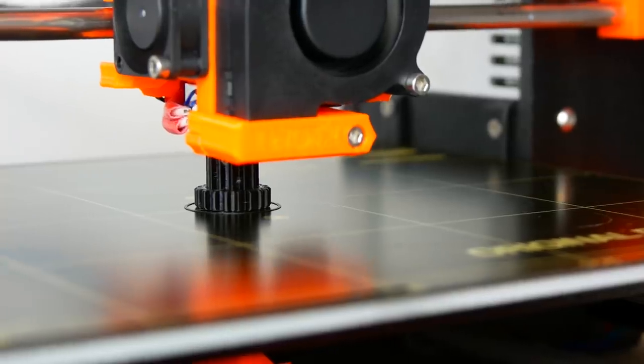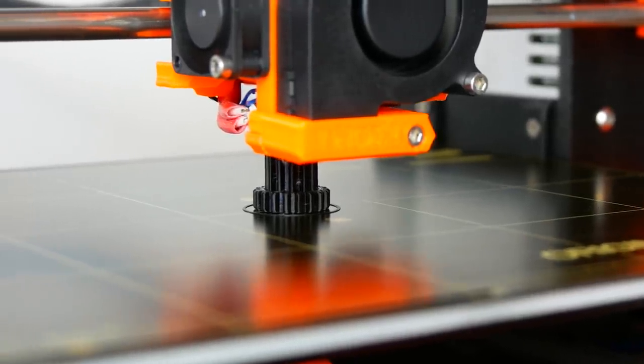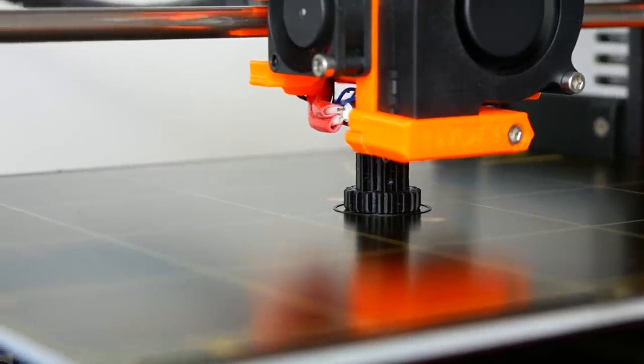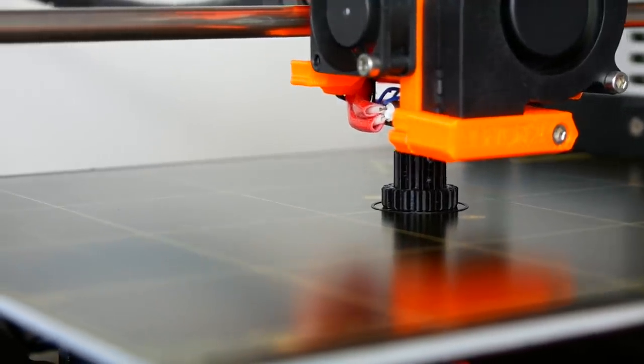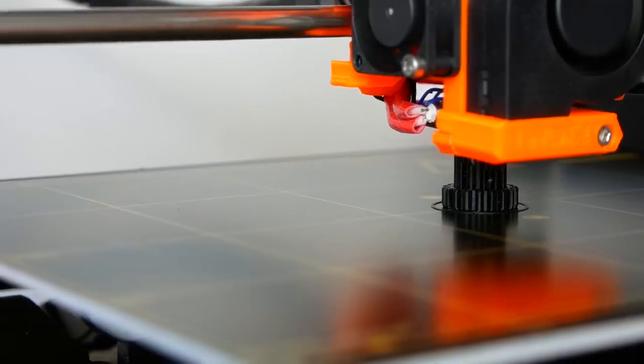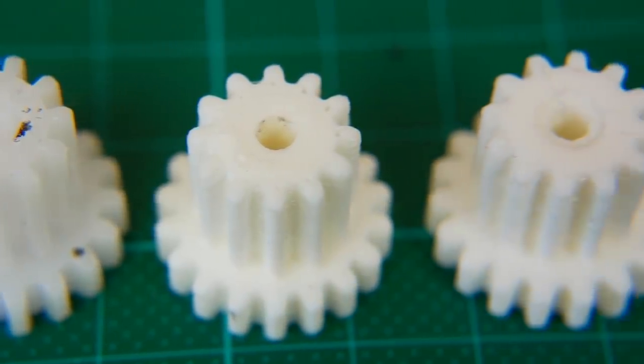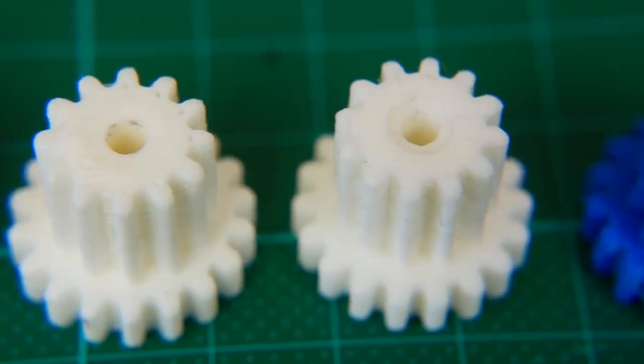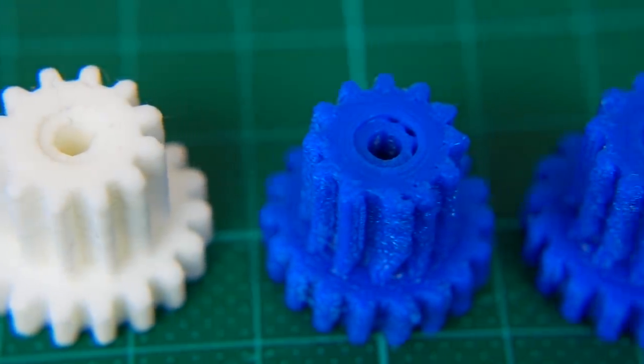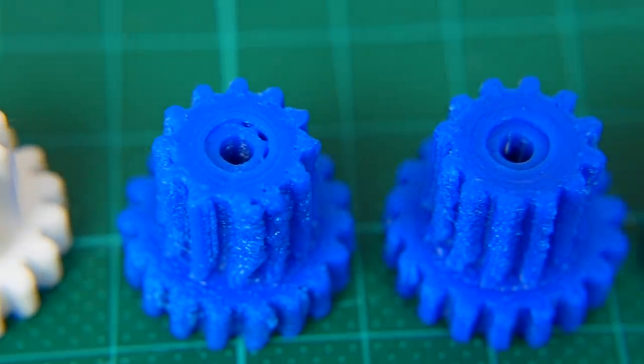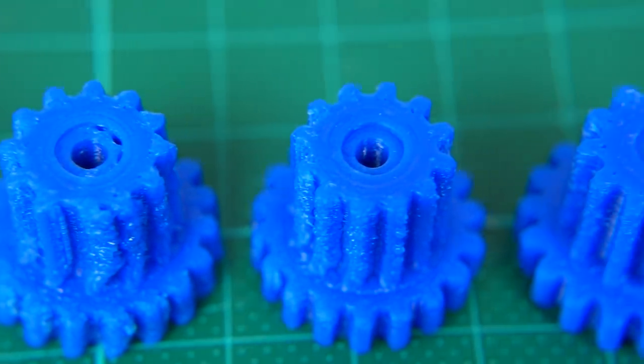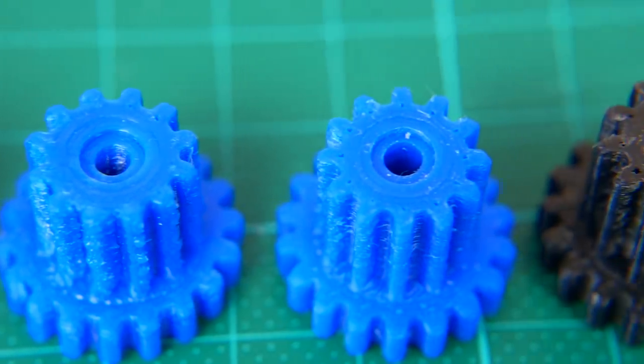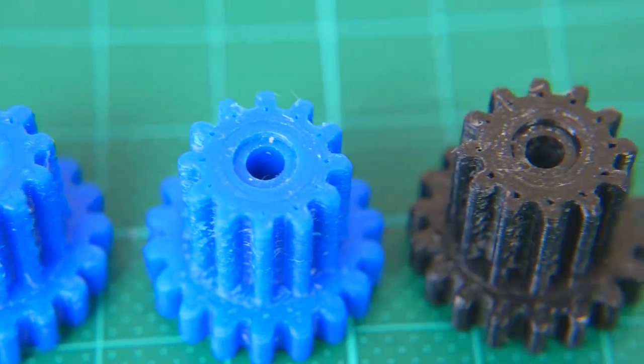PETG would probably give us a good print quality with decent strength, but I had some issues with layer adhesion with the brand I'm using. And since the torque in this gear is transmitted through shear between the layers, it's probably not a good idea. ABS would give us medium strength and good ductility, but the print quality is usually not the best. PLA at last gives us the best print quality with the highest strength, also between the layers. Unfortunately, it's quite brittle and I don't know how it will handle the moisture.